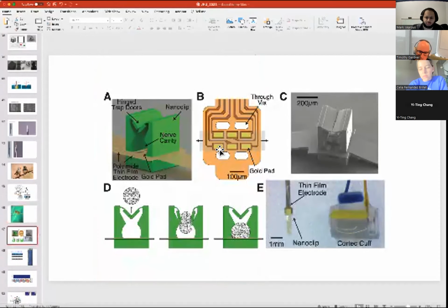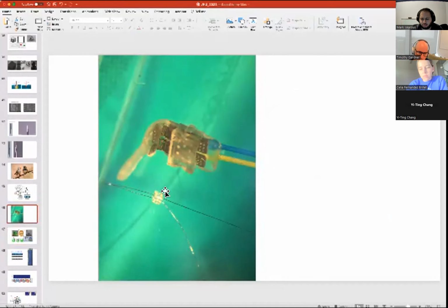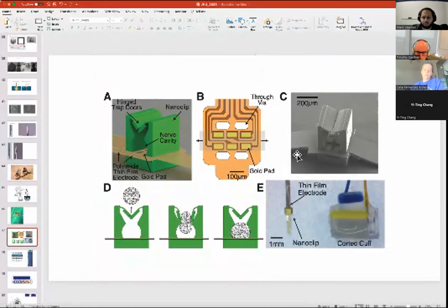That later was refined to include all microfabricated electrode traces. So instead of using that carbon nanotube thread from Rice University, this was Matteo Pasquali's magnificent, amazing material, we went to something that was fully microfabricated, so just a polyimide electrode with gold pads, and then we could 3D print on two sides of that thin film device, and that creates a mechanical clip that would hold a thin film electrode onto a nerve. And that's the finished product in size, and then again a kind of comparison to the commercial state of the art for nerves of that size.